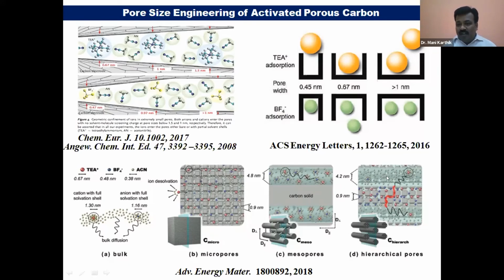We need to develop a material which has a hierarchical pore structure. It means this material should have high surface area as well as a pore size distribution. It has microporous as well as mesoporous. Suppose you have completely microporous; generally microporous is defined as less than 2 nanometers, and ultra microporous is less than 1 nanometer. If your pores are ultra microporous, less than 1 nanometer, that is also a problem. In one of the slides I showed previously, surface area of 2000, 2500 you can increase by decreasing the pore size. When you make ultra micropores, your surface area will increase.